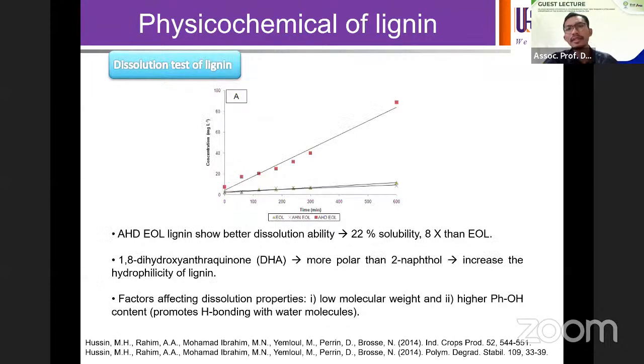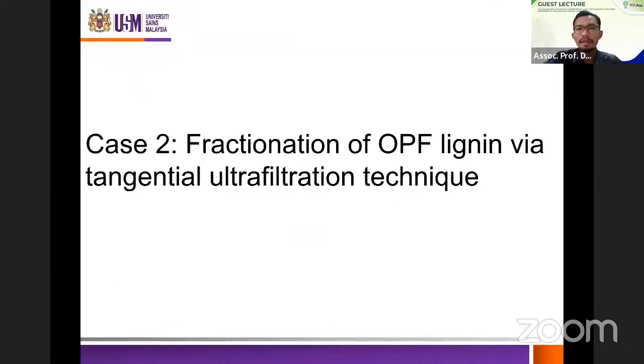And finally, we did the dissolution test. We just want to check whether the modified lignin improves in terms of solubility in water. Of course, after we modified the lignin, it had an increase of more than 20% in solubility rather than without any modification. So this is very good for our application, which means that the lignin that we have modified can be used in any application, especially that requires solubility in water.